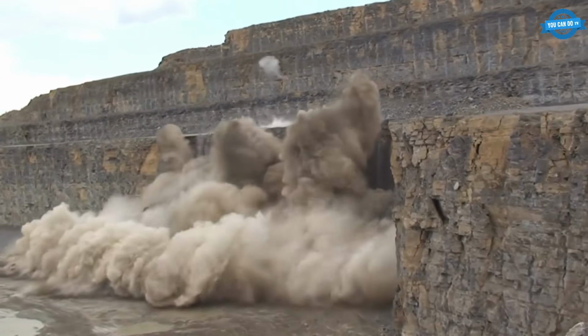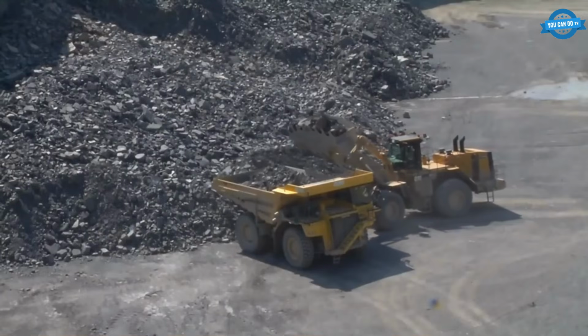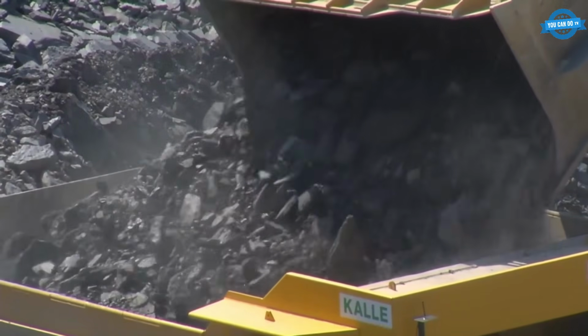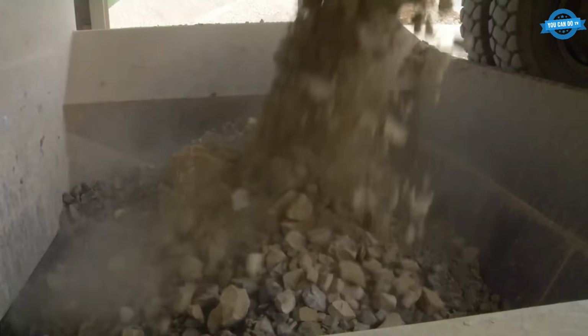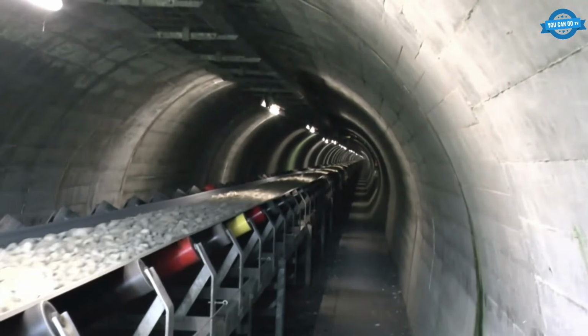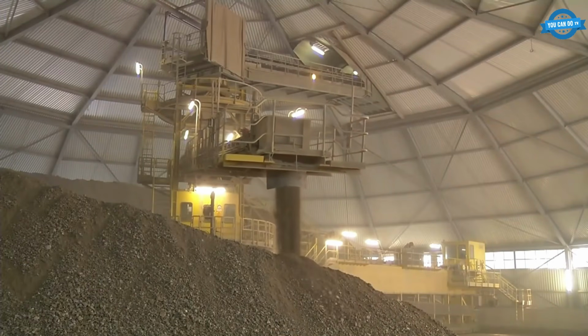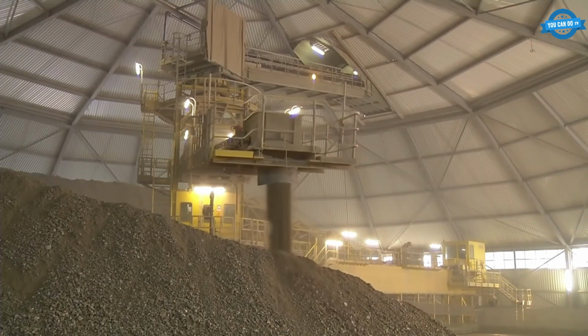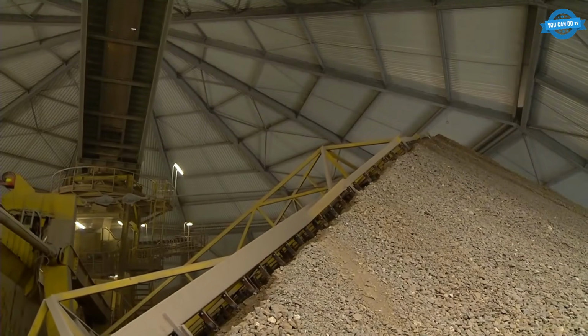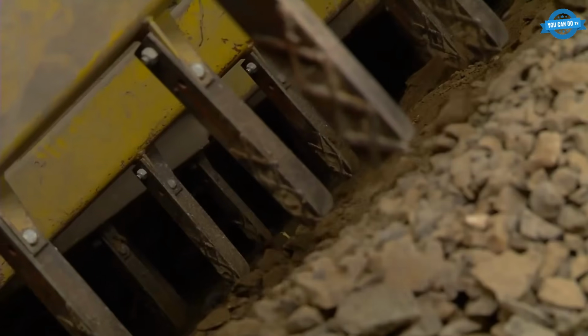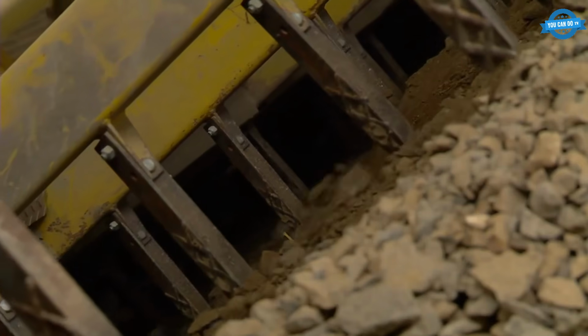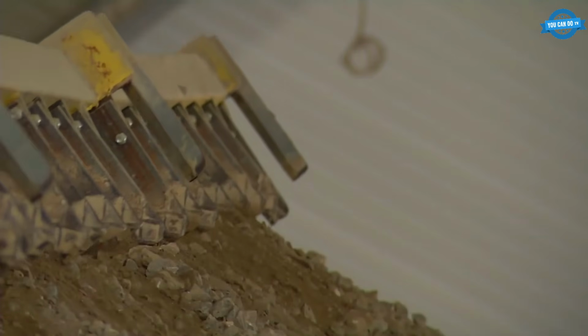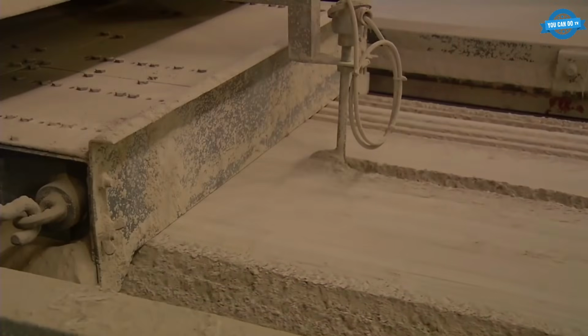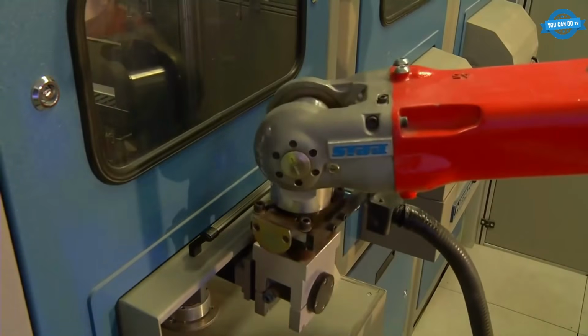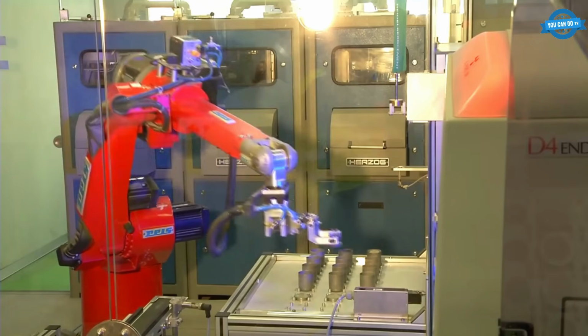Follow the rock from the pit, and you can watch chemistry happen in slow motion. Blasting opens the limestone face. Haul trucks feed the primary crusher. Conveyors run the material into pre-blend beds where it gets stacked in long parallel layers, then reclaimed sideways so the raw feed stays chemically consistent even when the quarry's own chemistry drifts. Cement plants live and die on that consistency. One bad batch of raw feed and thousands of tons of clinker come out useless, so the lab checks samples every few minutes and adjusts the mix on the fly.